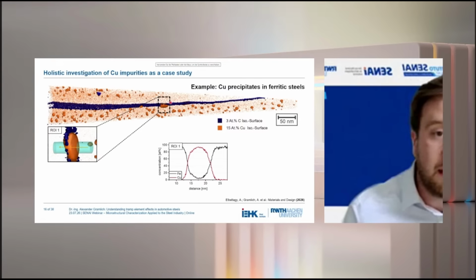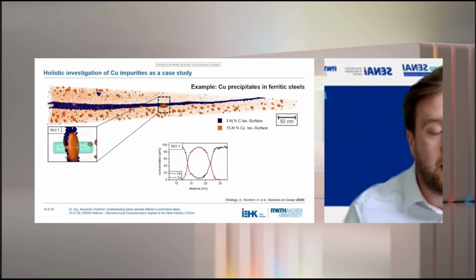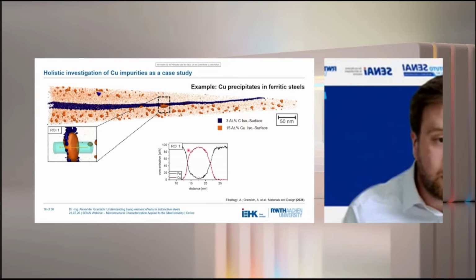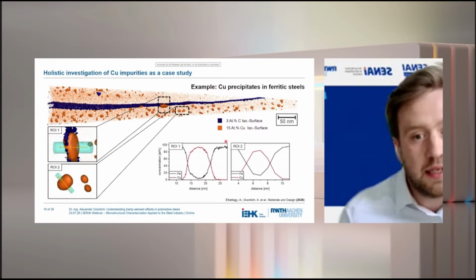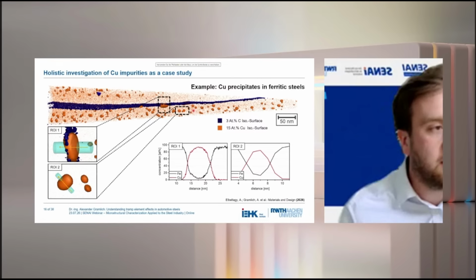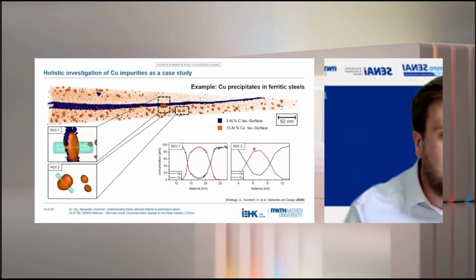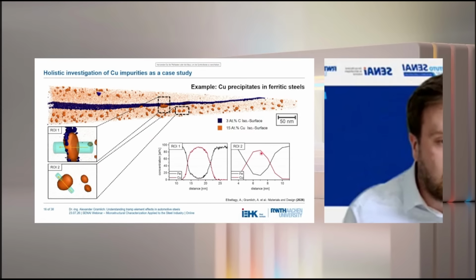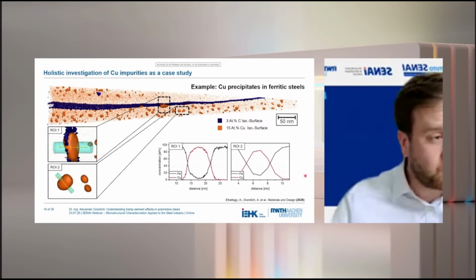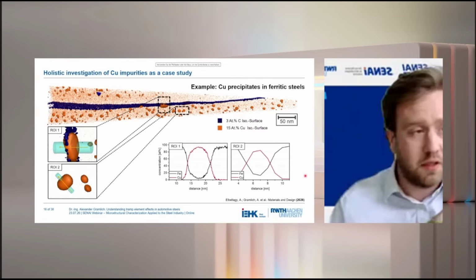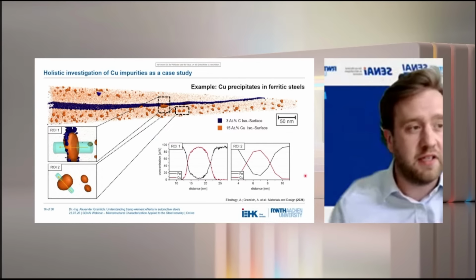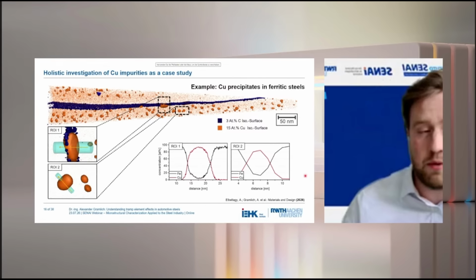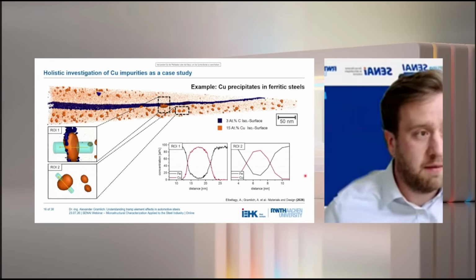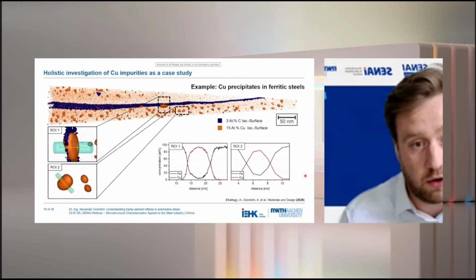And what we can see, for example, here at this interface, which we visualized, is a relatively large copper precipitate, which is already very, very high in copper. And the ones in the matrix, not directly at the interface, have a slightly reduced copper concentration, and also their size, their thickness, is approximately 50%. So you can already see in one sample, we have different types of precipitates, which are a bit contrary to what we learned on the schematic overview.